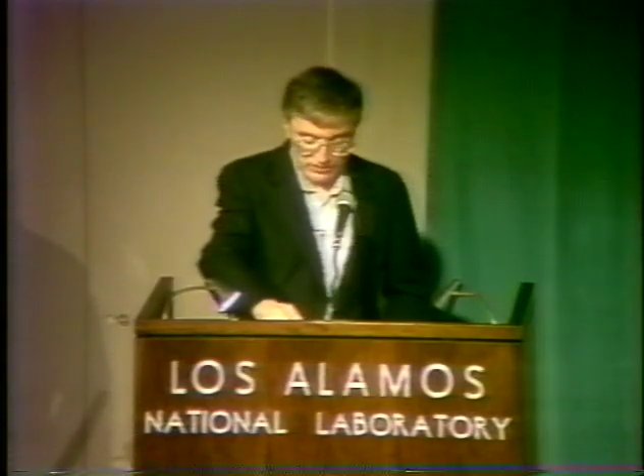We did not do anything quantitative on it, but we did try in January to get a blank experiment with a palladium electrode that we knew worked in regular water, and we did not get the heat in, heat out balance like we had expected. We did get some excess heat. So that is still open for investigation. That experiment is set up and running again right now. But the heats were fairly small.